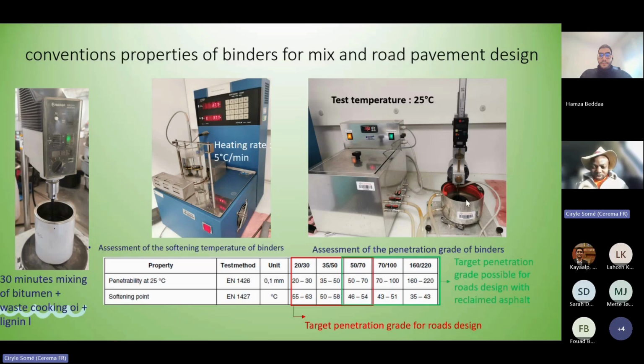For example, for road application, I colored here in a red rectangle the type of bitumen we use. When I write here bitumen 20-30, it means that the needle penetration is between 20 and 30, and the softening temperature is between 55 and 63. Those two tests allow us to classify bitumen and to choose the right bitumen to build a road in the right climate. So we perform those two tests on the blend we produce by mixing bitumen, lignin, and cooking oils.